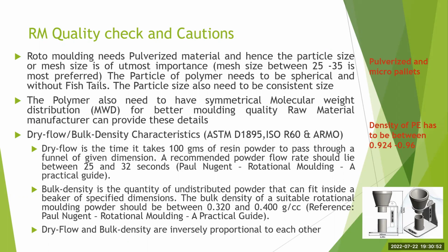If you're grinding a powder, your mesh size needs to be very consistent and of the same size, near to its requirement. The molecular weight distribution is a property of the raw material supplier. We need to check whether the molecular weight distribution is consistent or it doesn't have a wide range. It should be a narrow range. The molecular weight distribution has to be very narrow. It should not be very wide.